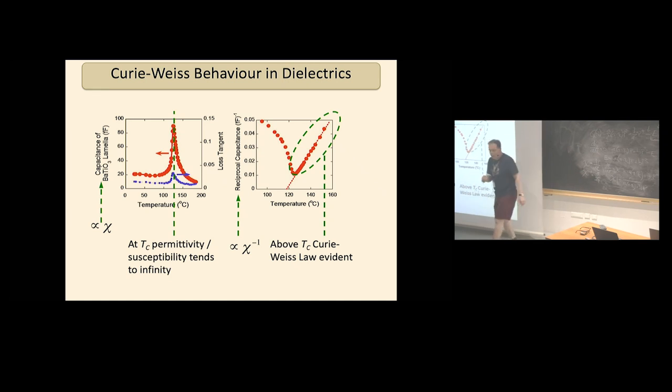I should also say that for a second order phase transition, if we put in the equilibrium value of polarization here and worked it through, you would end up with the same sort of expression, but it'd be 1 over minus 2A(T minus Tc). So the gradient goes from positive to negative, and it actually increases by 2. It might be 2 over, I might have got that wrong. Okay, and you can see here that this is a shallow gradient. This is a relatively steep gradient as you go from above Tc to below Tc. Okay, pretty cool.